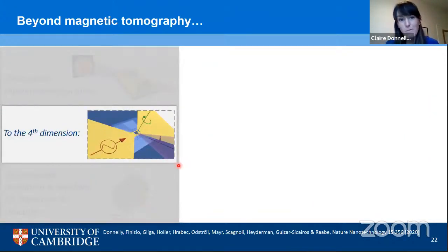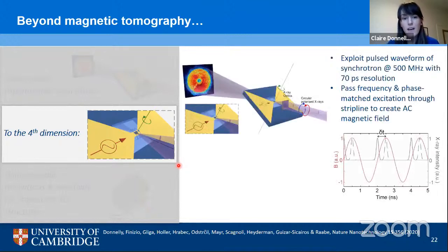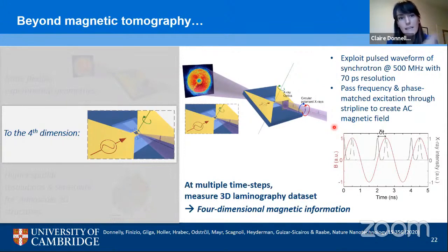And that is when we think about our wish to go to the fourth dimension. Now that we can look at flat extended samples, what we can actually do is pattern our samples lithographically, meaning that we can pattern strip lines onto our sample with which we can excite our magnetization. And that's what we do here. We pattern our strip line, we use the Oersted field of our strip line to excite the magnetic state of our disk. And by frequency and phase matching the excitation, so this AC current, to the time structure of our X-rays, we can perform a pump probe measurement, measuring a laminography data set for many different time delays with respect to the main time structure.